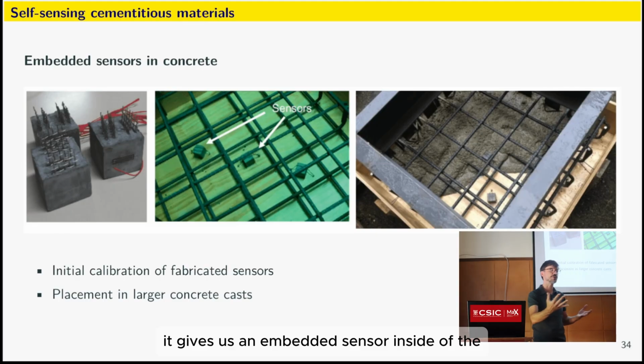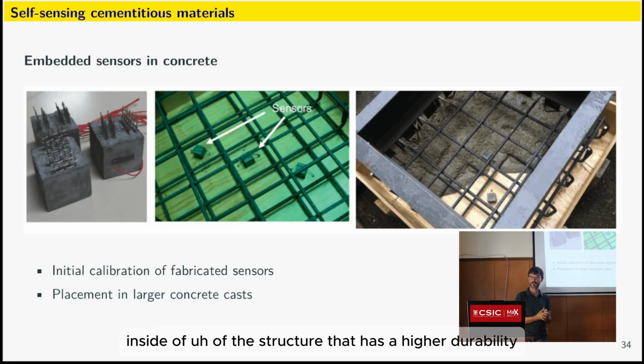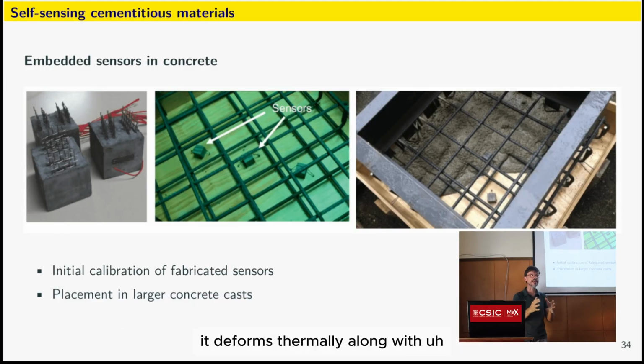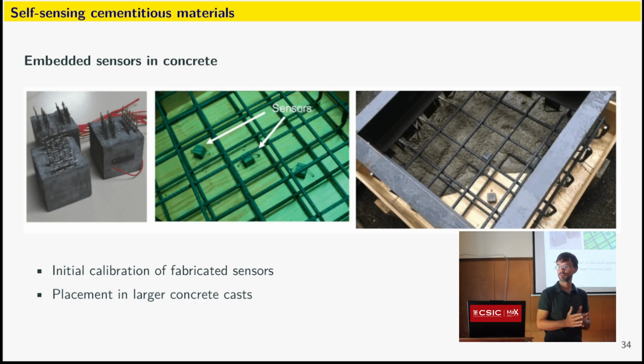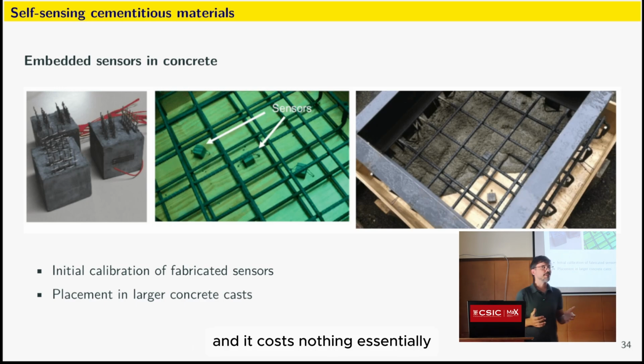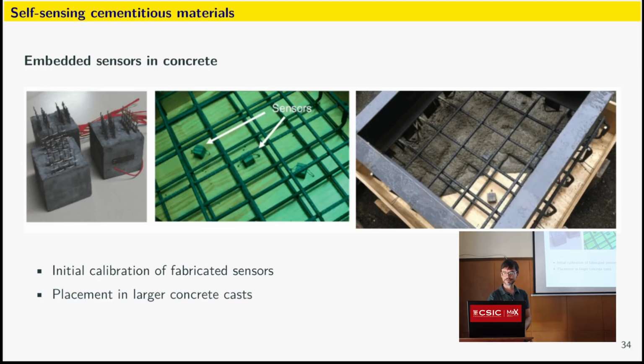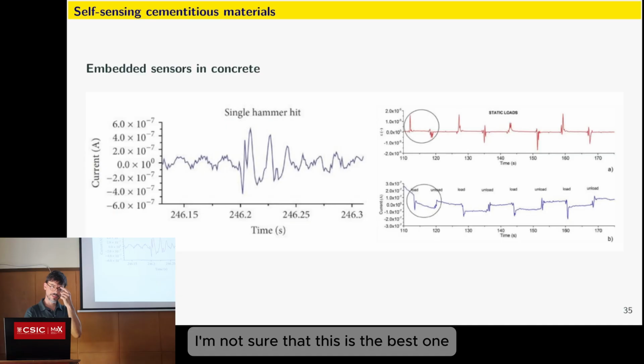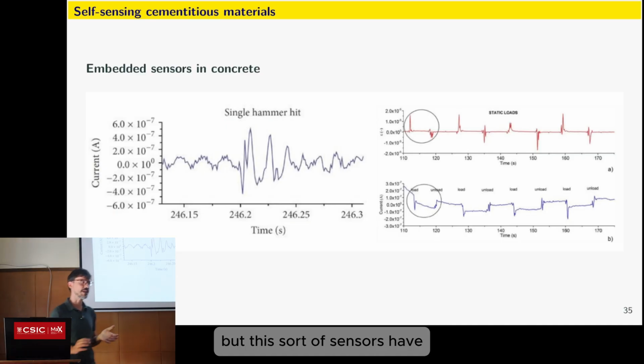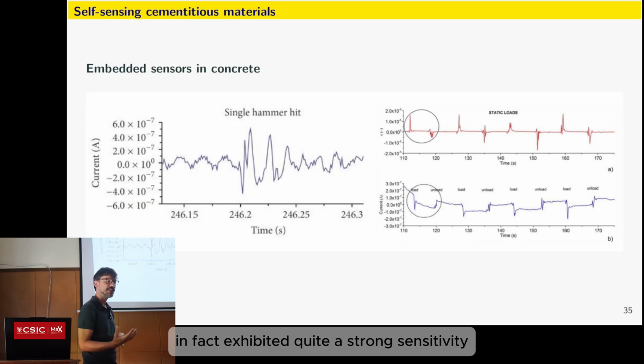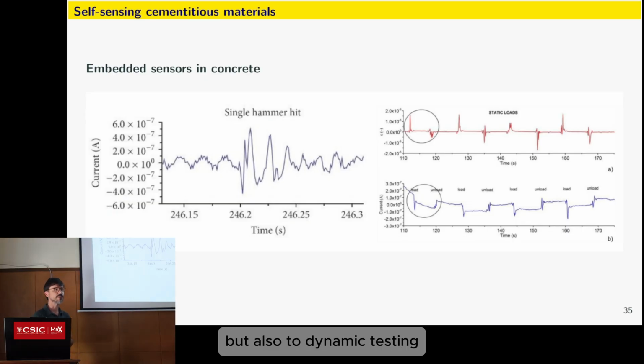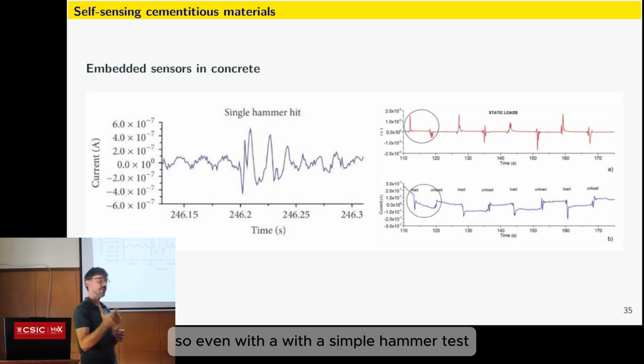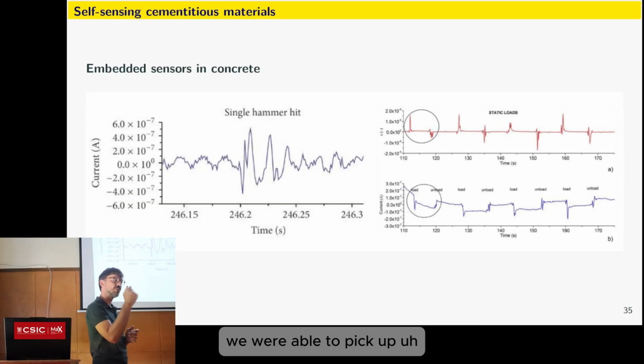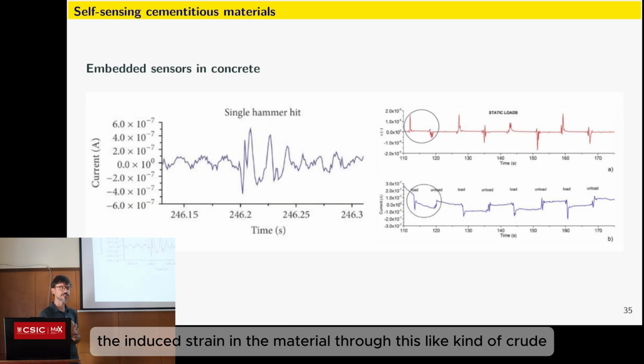So what does this give us? It gives us an embedded sensor inside of the structure that has a higher durability. It deforms thermally along with the surrounding structure, and it costs nothing essentially. But that is one option. I'm not sure that this is the best one. But these sort of sensors have in fact exhibited quite a strong sensitivity, not only to static testing, but also to dynamic testing. So even with a simple hammer test, we were able to pick up the induced strain in the material through this kind of crude sensor.